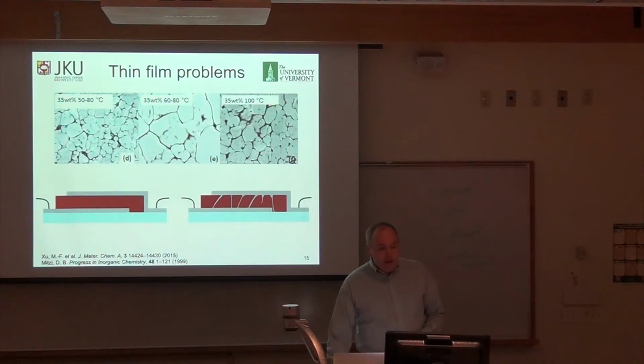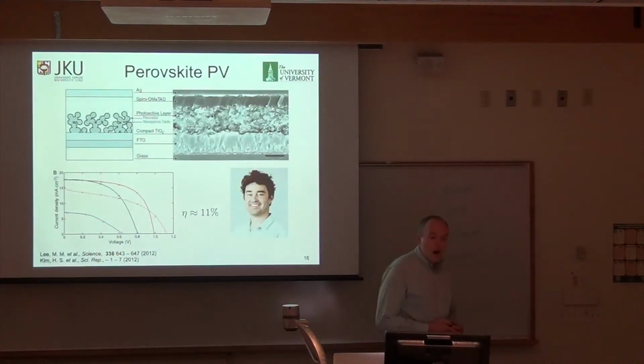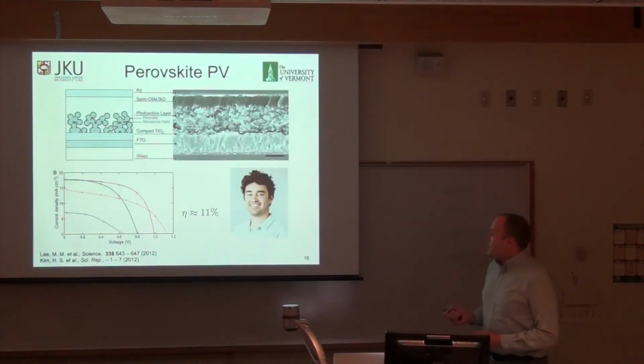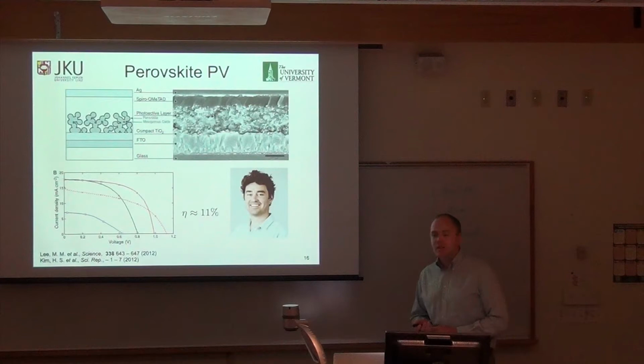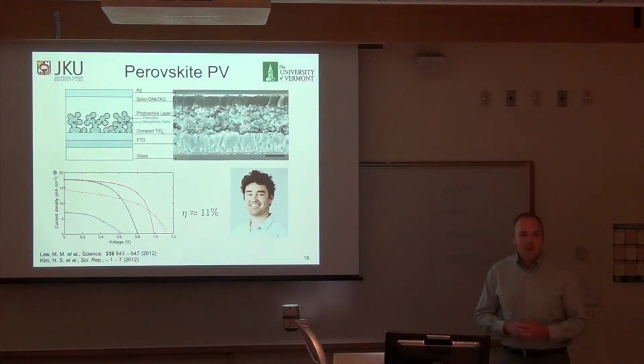They were about 5 years too early, because in 2012, Henry Snaith from Oxford, as well as Michael Grätzel from EPFL in Lausanne, demonstrated that these perovskite materials, if you can get the films done right, can be very, very good for solar cells. This was the first demonstration. You can see that they used a sintered titanium nanoparticle mesoporous structure. The reason they did this was because they were coming from a dye-sensitized solar cell background — these two groups had investigated dye-sensitized solar cells, which have a mesoporous titanium structure.